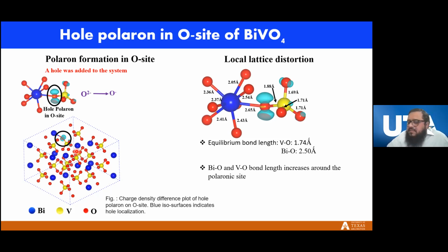Most of the common experimental work that I have seen so far considers metal-oxide photoelectrocatalysts as photoanode materials. In that sense, the first scenario that you mentioned, that electron mobility should be better, meaning it has lower effective mass and the hole should have higher effective mass, can be considered, even though I'm not very supportive of this kind of statement for other reasons.